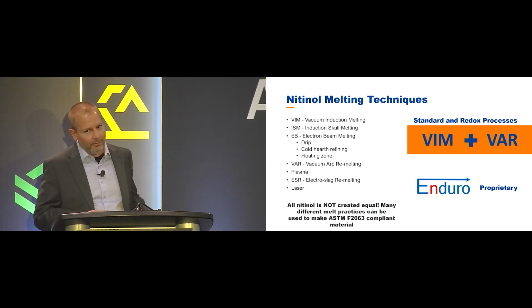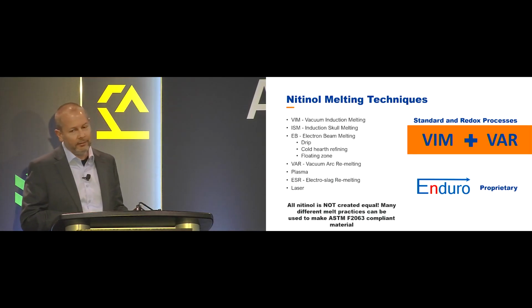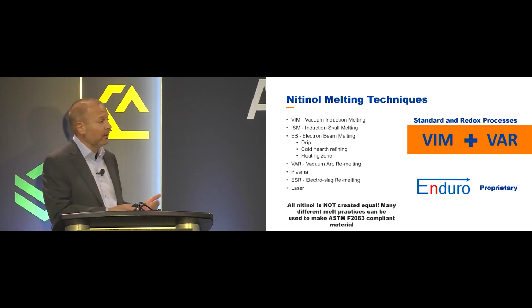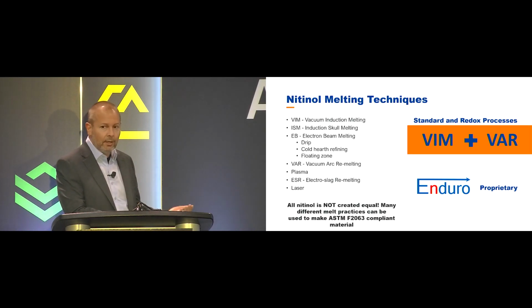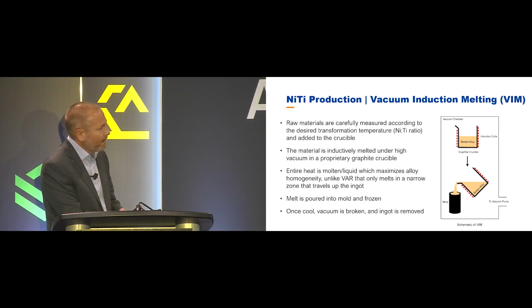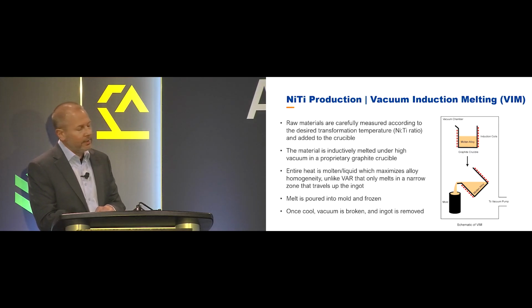And I can look at a micrograph. We have to test it for that F2063 to look at inclusions. And when I look at our material versus someone else's, it's very clear there's a difference. And I'm not saying necessarily one is better than the other, but you can see a difference in the material just by how it's melted. Nitinol is not nitinol. So our production method, we start with a vacuum induction melt. We measure a charge out very precisely.